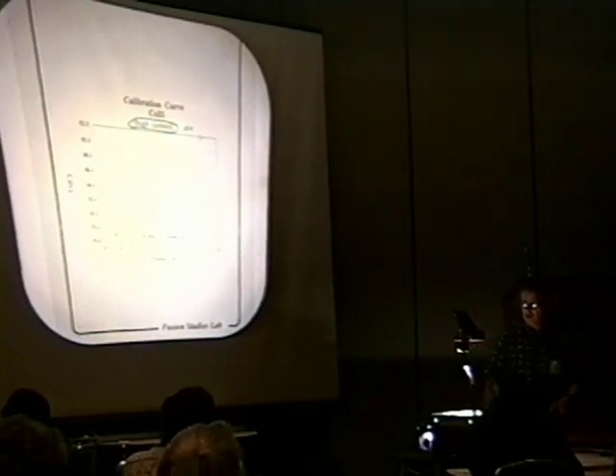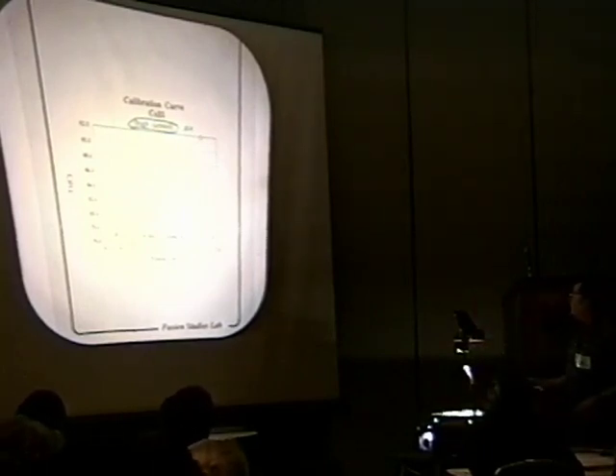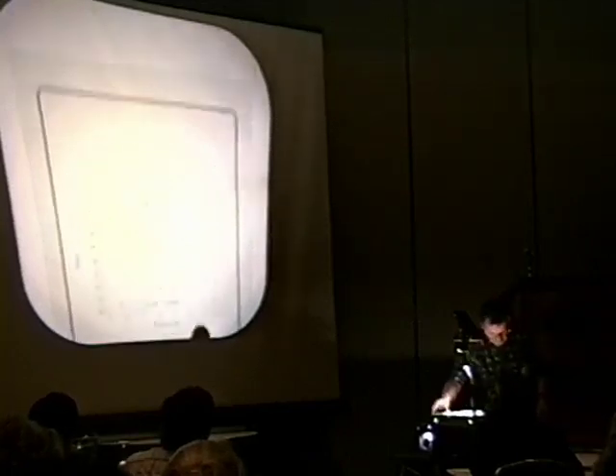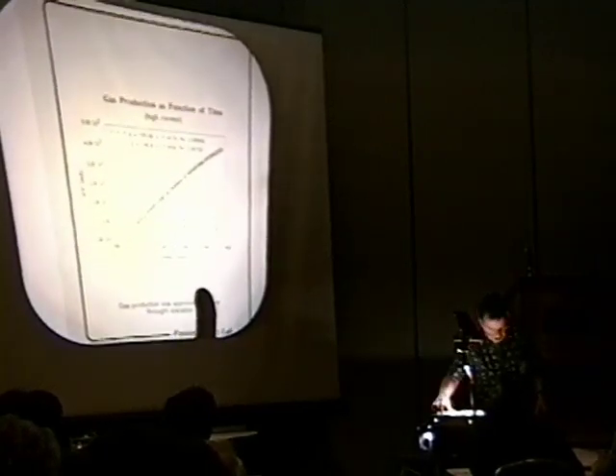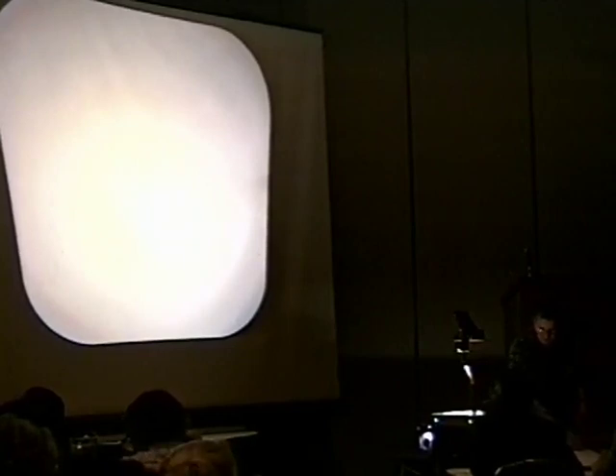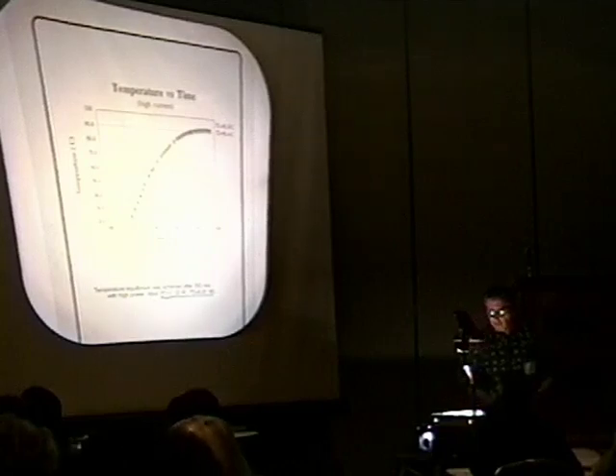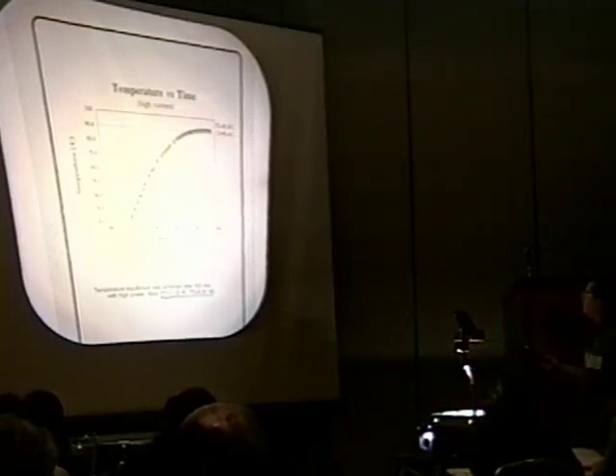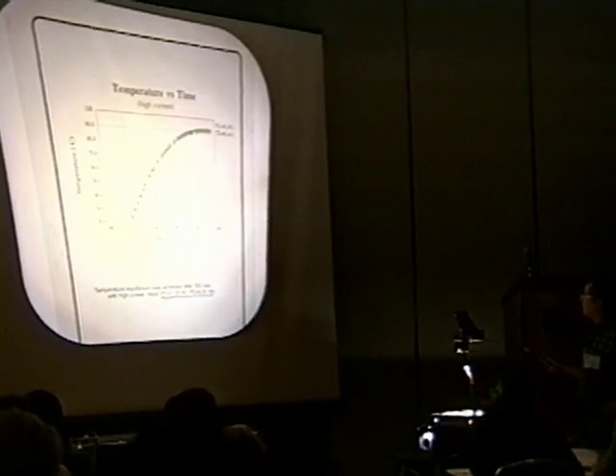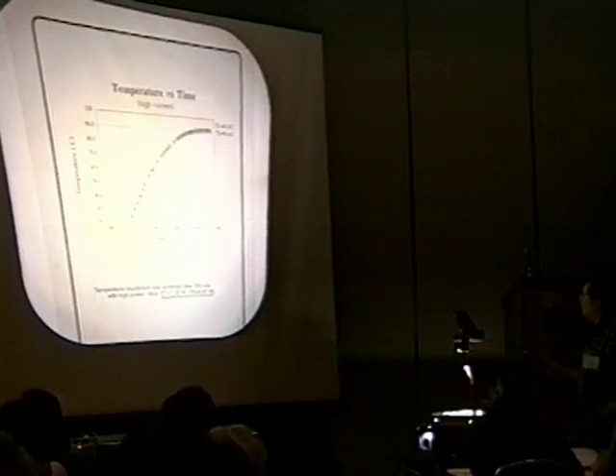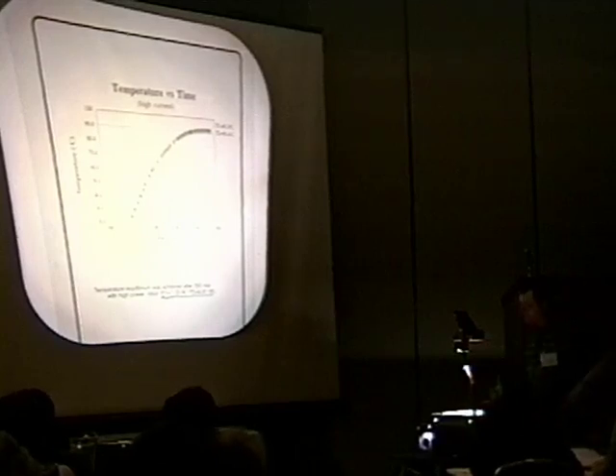This same type of effect is much more noticeable with higher currents, and so we've done similar experiments with currents an order of magnitude higher, and again, cell calibration appears fairly linear. Gas production deviates a little bit, but not greatly in linearity. And again, the time history is shown here. We're now, with this type of arrangement, getting up to fairly high temperatures, 90 degrees or so, equilibrium after about 400 minutes of a typical run. These two curves shown here are for power inputs of around 7 watts.